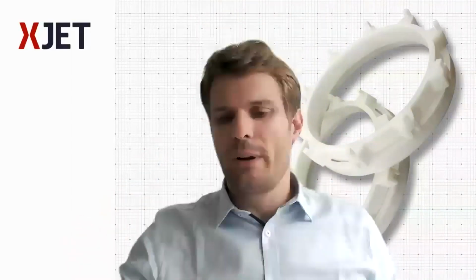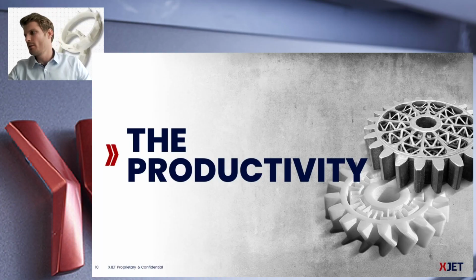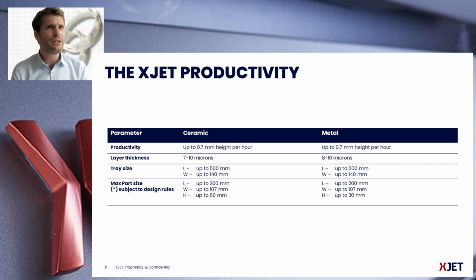So just one quick slide about the productivity to show you the dimensions of what we can print and on what we print. In terms of productivity, we print at around, and this is based on the precision of the printing job, 0.7 millimeters per hour. The layer thickness, as we mentioned, is at around 8 micron. A tray size, the one that you just saw, is at 500 times 140 millimeters. And the maximum part size, and it's subject to design rules, of course, but we always can stretch in any kind of direction, is 200 times 107 times 60 on ceramic, and on metal, 200 times 107 times 30.